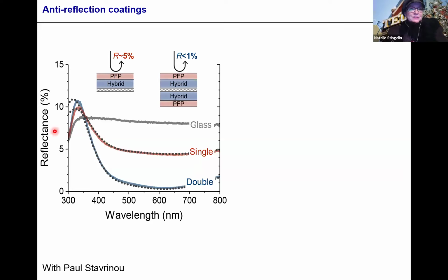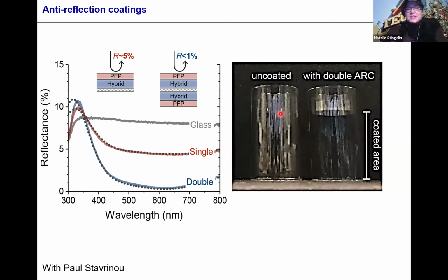If you have glass, the reflectance—then we do the 2 layers, 4 layers—you see we drastically reduce actually the reflectivity of this glass. And you see that here.